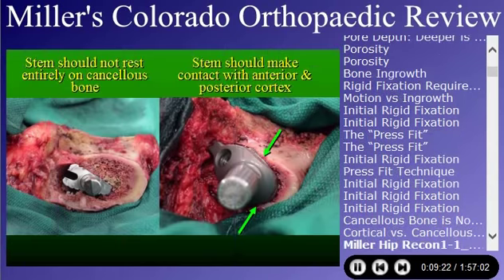And what we used to do is, if you see in the slide on the left, we used to put these porous-coated implants against the cancellous bone because we thought that bone was, quote, more metabolically active, that the bone cells are more apt to grow in. And it's true, they did. The only problem is that that cancellous bone with loading would shear and fall apart. And what we found out is that the cortical bone is just as metabolically active, and you have that loading onto the outer cortex, which is simulating the native hip. And that's the type of contact that we need. So if you're using any implant, you want your implant to be loaded against the anterior and posterior cortex.